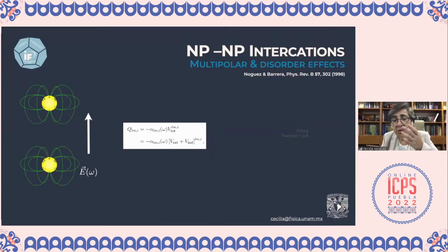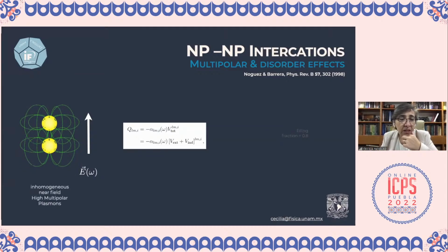Now, as I told you, another important thing is how the nanoparticles interact. And let's think that you have 2 spherical nanoparticles and you have an external field. As I said, you have a kind of dipolar distribution of the surface charges, and this is the electric field that you can find for each one of these. However, when you have the particles very close to each other, what happens is that the electric field induced by this dipole also interacts and contributes to the polarization of the second particle, and the same for the second particle. The electric field that is induced will contribute to the first one.